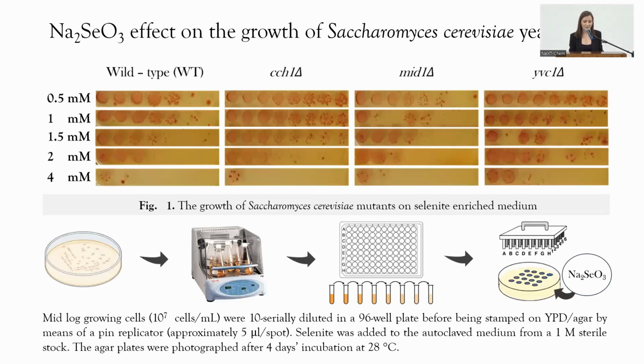To assess the sodium selenite effect on the growth of Saccharomyces cerevisiae yeast cells, we have serially diluted the culture of each strain in a microplate, and then we stamped the culture on a YPD agar media, which was supplemented with sodium selenite in a range of concentration from 0.5 to 4 millimolar. One of the first observations is that the cultures changed their color, which means that selenium was indeed reduced. How do we know that? The cultures turned red, which is an indicator of selenium nanoparticles presence.